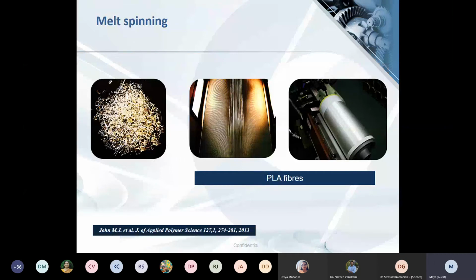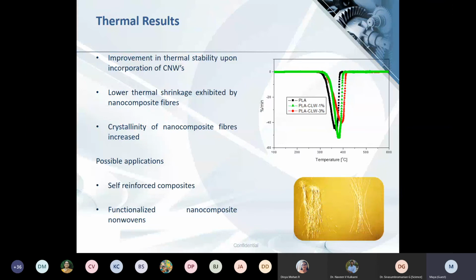Some of our important results are that we saw improvement in thermal stability by the incorporation of cellulose nanowhiskers. The thermal shrinkage of the nanocomposite fibers was much lower, so this has applications in the textile arena. There was also improved crystallinity. Now, the possible application is that these fibers can be converted into nonwovens. And then you have a nanocomposite nonwoven mat, which can be used for self-reinforced composites. Another option is that while you are extruding in the filament extruder, while you're forming the fibers, you can add additional ingredients, additional functional agents. It can be flame retardants, it can be antiviral agents, so that you have functionalized nanocomposite nonwovens. And an example is that you can use these functionalized nonwovens for making filters in masks and so on.